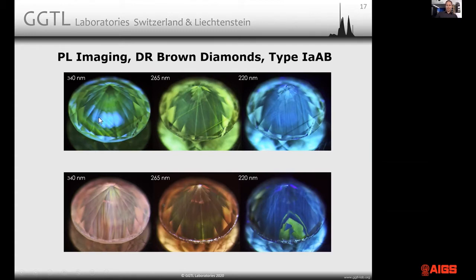You can see the deformation-related graining here. So these bands that you see here on the top spectrum go straight along the slip planes. They contain usually at least H3 centers. So you have H3 and H4 centers in these stones that cause predominant green fluorescence that's very commonly seen in brown diamonds, more or less intense. You can have brown diamonds that have such strong green fluorescence that they basically have the same effects as a green emitter, but just with a brown body color.